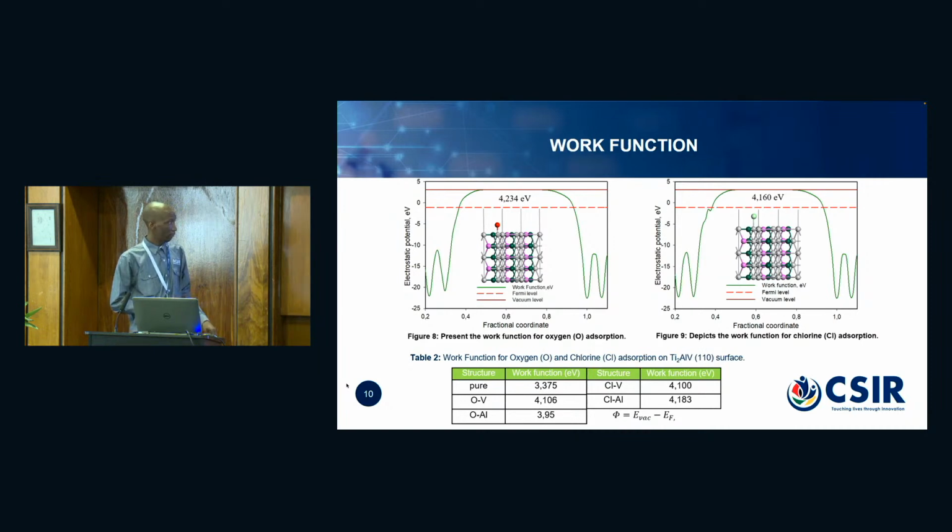First, we measure the work function before the impurities were on the surface. And then we found that including the impurities on the surface in fact increases or induces the work function. So it means the impurity will form a dipole moment on the surface, and then it will be very difficult to remove an electron afterwards. So by checking the magnitude, after impurities have increased the magnitude of the work function, and it's defined by those kind of figures over there.